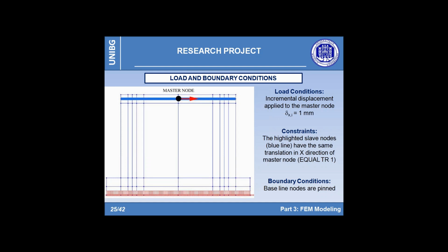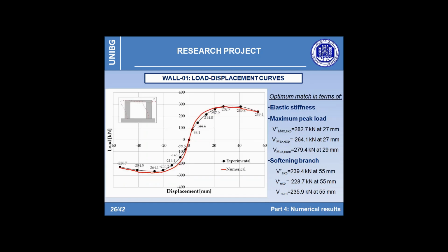For each of the three tests, the comparison in terms of load-displacement curves is presented, and in particular in the next slide, the black line reports the envelope curve derived from the experimental cyclic loading. As previously said, the numerical simulation is only monotonic, and so in red is the capacity curve, equal for both directions given the symmetry of the specimen.